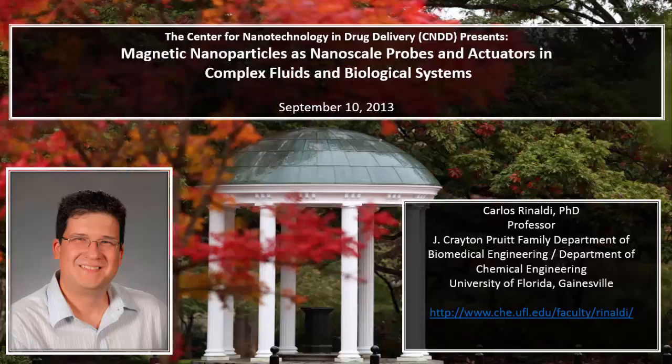And actually, if you look at the Debye model, you take advantage of the fact that the frequencies that we're using are rather low. You can expand the Debye model into something that looks like this. When you're undergoing the gelation transition, the hydrodynamic drag on the particles is going to increase dramatically, very quickly. So that means the relaxation time is also going to increase dramatically.